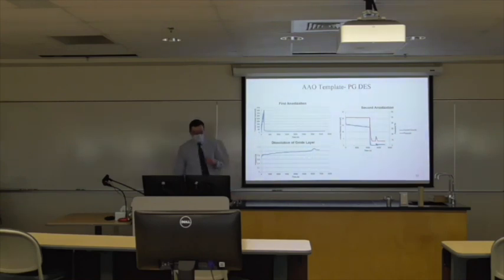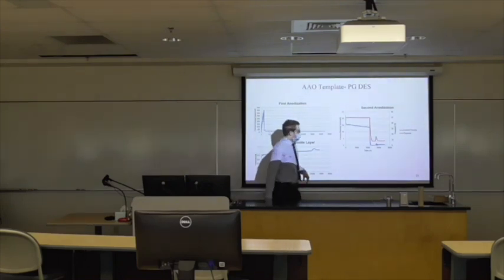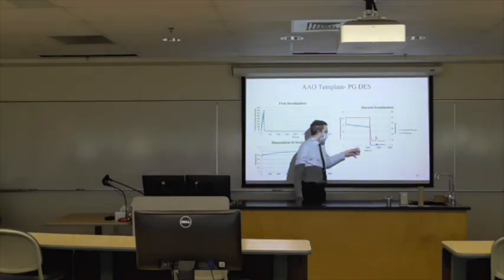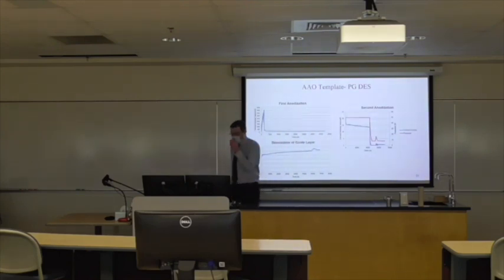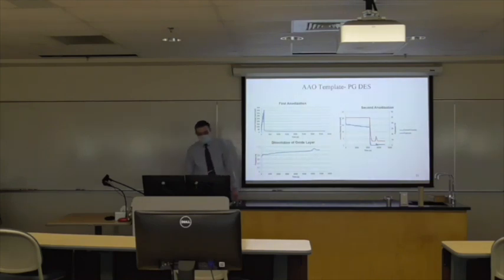this bump in the voltage occurs on the graph, but it was exhibited, for example, in Stein's papers on the subject. And also we can see from these ionizations that when we're dropping the potential used, the current density also drops. So it's not going to make a much larger layer on the bottom after you're done with your 50-volt system. But then with the barrier layer thing, we slowly can reduce the thinner barrier layer to more easily allow the deposition in pores.